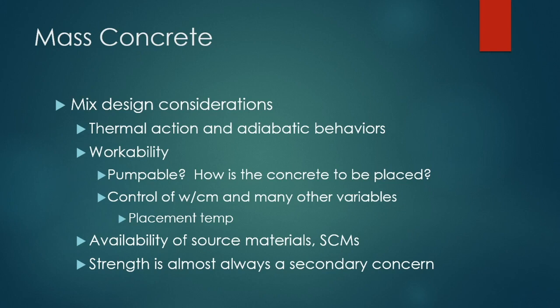Sometimes certain good supplementary cementitious materials that could be a benefit in mix designs might not be available. For example, in certain parts of the country, slag isn't available. It's just not an option. Slag happens to be a very good supplementary cementitious material for mass concrete. So people in those areas have to use another type of supplementary cementitious material that is going to keep the heat of hydration down. A lot of these considerations are geared towards keeping the heat of hydration low from the beginning. And then, as I said earlier, strength is almost always a secondary concern. Pretty much any mix design is going to get to the strength that is needed for that project.